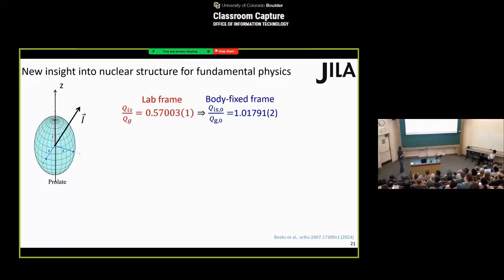This ratio is first measured in our lab frame, but we know that the nucleus has some angular momentum, so it's rotating around and gives us an averaging effect. If we transform back to the body-fixed frame of the nucleus, we can learn about the quadrupole deformation ratio between the ground and the nuclear excited state. Now you can see that the ratio is very close to 1, indicating that the quadrupole deformation of the ground and excited state is about the same, but we can measure this very small difference very precisely.